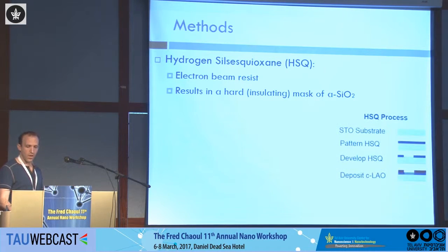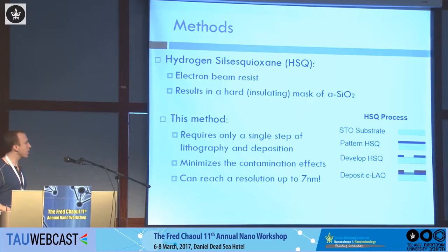And this is what we do in the HSQ process. We take the substrate, we pattern the HSQ, develop it, and immediately can deposit the crystalline LAO, and it will be conducting only on the part where there's no HSQ. So this method requires only a single step of lithography and deposition. It minimizes the contamination effects, and if you have the right E-beam, it can reach a resolution of up to 7 nanometers,